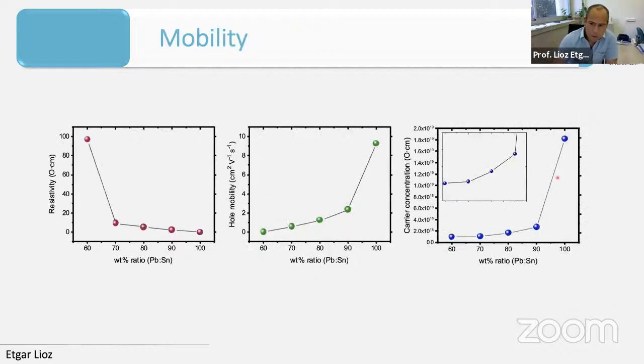On the other hand, when we check some Hall effect measurements, you can see that when you put more and more tin, indeed, you have much higher Hall mobility, which means that the material becomes more and more p-type. And this is actually something that is not so good for us, since we want to get a much better conductivity as an N-type material. And in the same case, if the Hall mobility is going up, also the carrier concentration is going up when you put more and more tin. So as I said before, on one side, the tin helps you to stabilize the structure, gives you a wider band gap, but makes your material more and more p-type, more hole conductor instead of electron conductor.